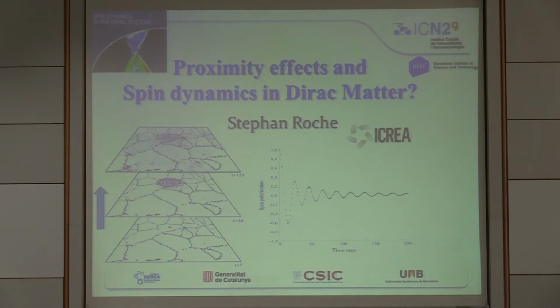Okay? So let's start with this picture, which shows how initially out-of-plane spin polarized wave packets propagate in polycrystalline graphene under the action of an in-plane Rashba spin-orbit coupling field, which is induced by the substrate, a typical situation that we find in the experiment. As you see on this snapshot of the time evolution, the wave packets extend from the initial injection point and diffuse and scatter in space because of the disorder grain boundary. And simultaneously, the spin polarization precesses and eventually relaxes in time due to disorder, due to many phenomena.